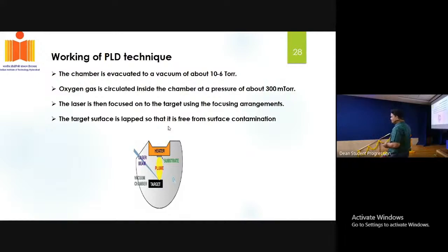Otherwise, particularly when you try to deposit the metallic thin film, these oxygen atoms will go and interact with your thin film. Because of that, if you require a pure metallic thin film, instead of getting it, you may get an oxide thin film. That's the reason why it is very important to evacuate the entire chamber with ultra high vacuum at least, or otherwise, if that is not available, with high vacuum, so that you get the pure film.